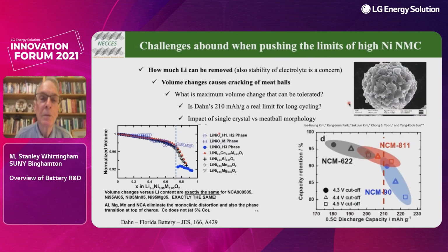Now, we want to push the limits of the high nickel as far as we can. The question is, how much lithium can we get out? We know we can get it all out if we go to a high enough voltage, but this electrolyte is not stable there. We also know there's quite a lot of data now by my colleague Jeff Dahn, who's speaking next, that there are large volume changes, and that these volume changes probably cause the cracking of these meatballs.